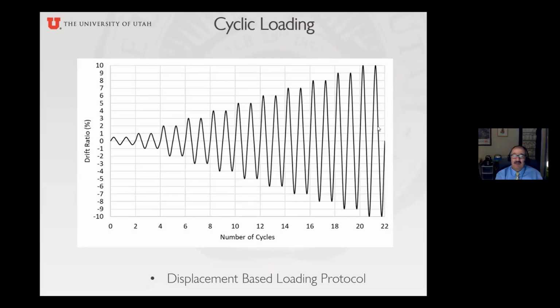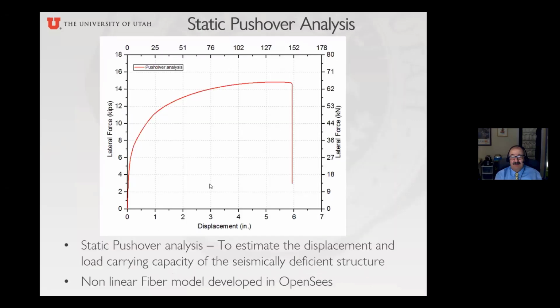So this is our cyclic loading. We apply 2 cycles at increasing drift ratios, anywhere from 0.5% to however far it can go. It's 2 cycles, and we found out 2 cycles is a good number, because if you do 3, you're fatiguing it too early. So you don't want to put too many cycles starting from the beginning, because as you can see, these cycles are getting pretty large. So it's displacement based, because you want to make sure you capture the peak force.